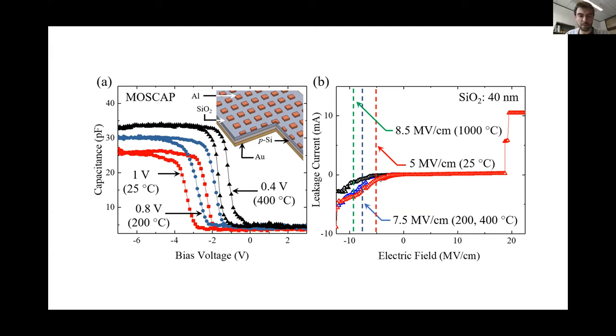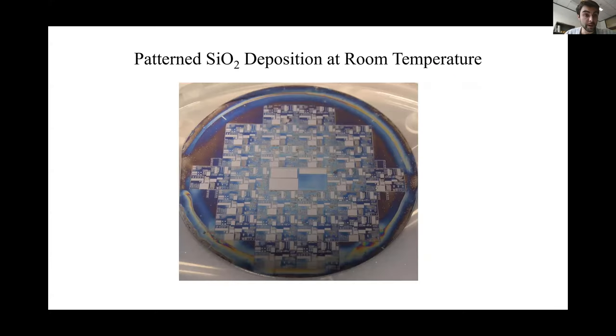You can obviously do high temperature thermal processing and just improve characteristics of these films, but the key point here is that this can be done at 25C. Okay, so now, since we can do it at room temperature, why don't we use a PR and actually deposit patterned SiO2 on a wafer? So this is not the best image that we have, but I think this is our first trial. But the key point is that you can use a PR. You can just make any pattern that you want and deposit SiO2 through a photoresist, which is amazing in our opinion, because this skips a couple of processing steps and allows you to do very fast deposition of patterned structures.